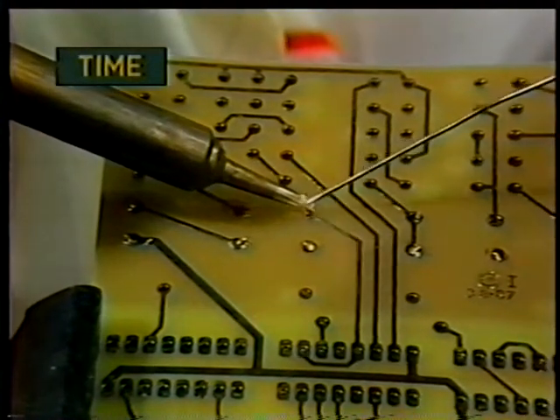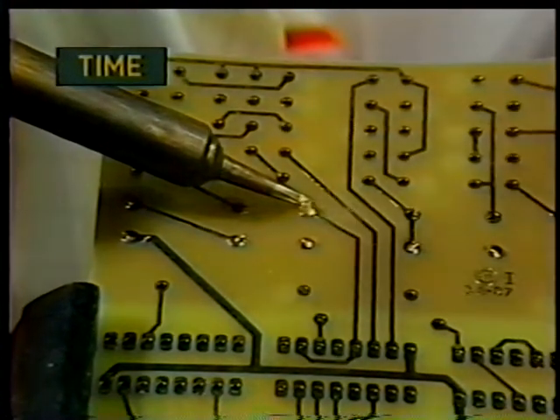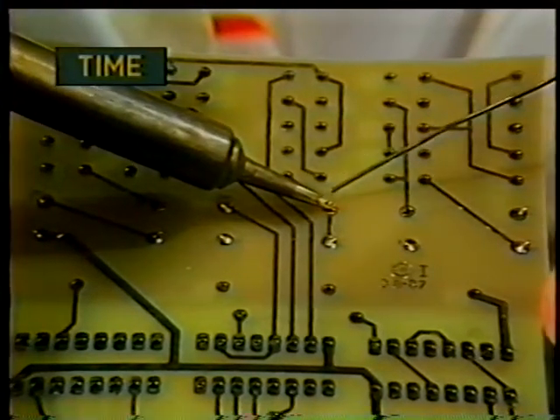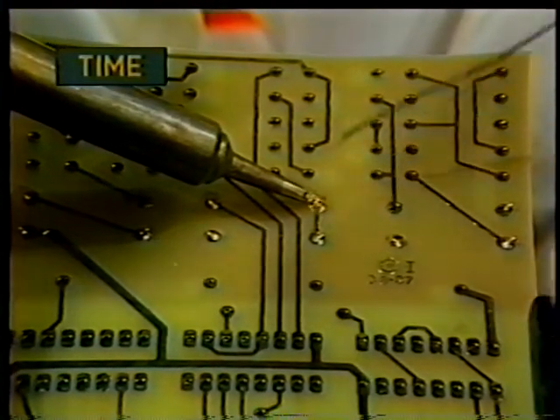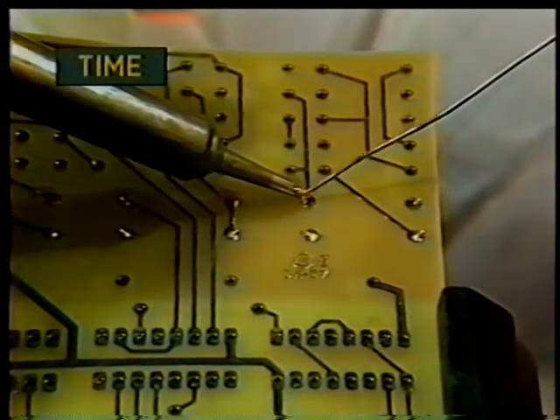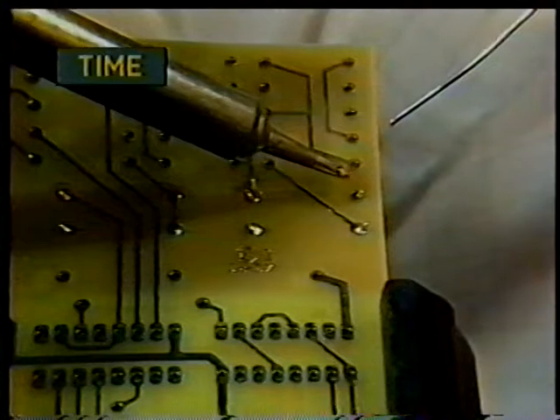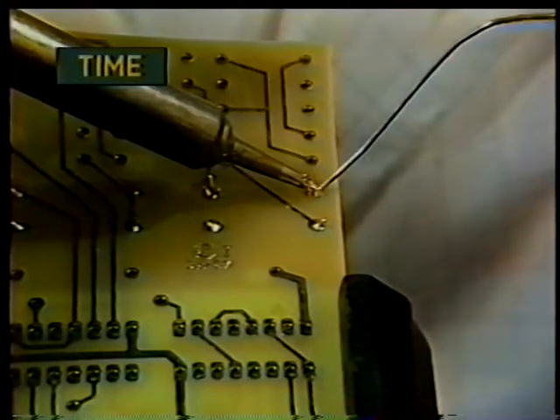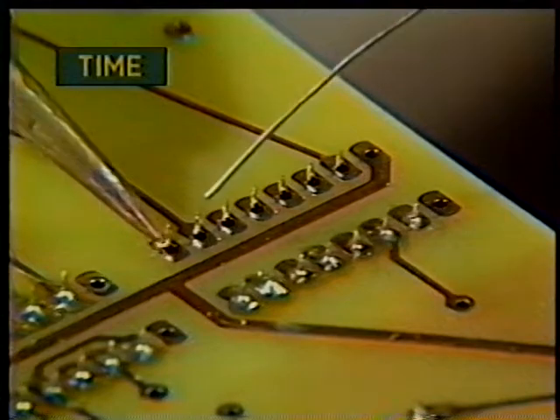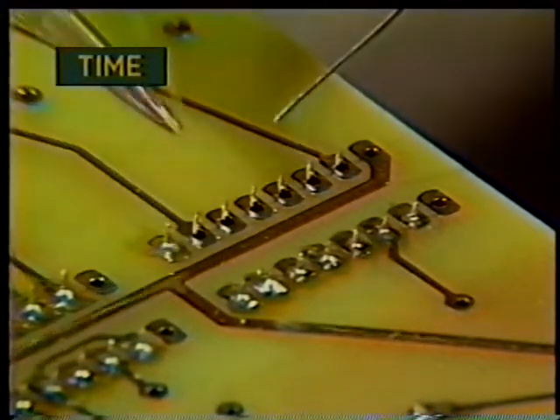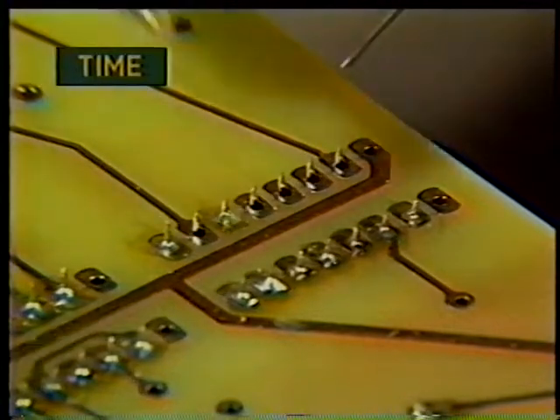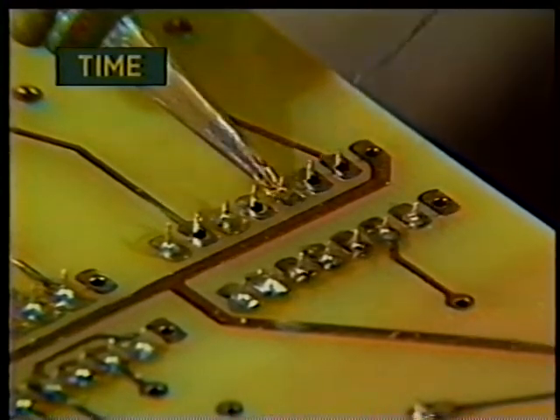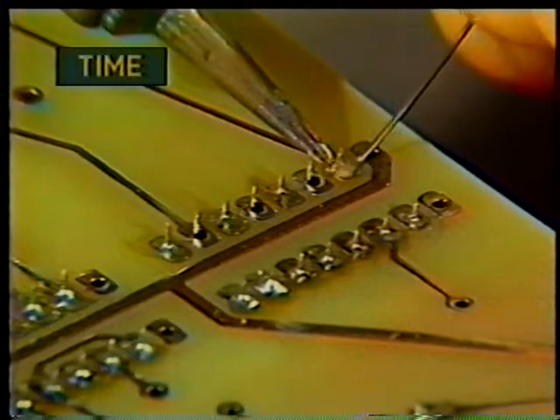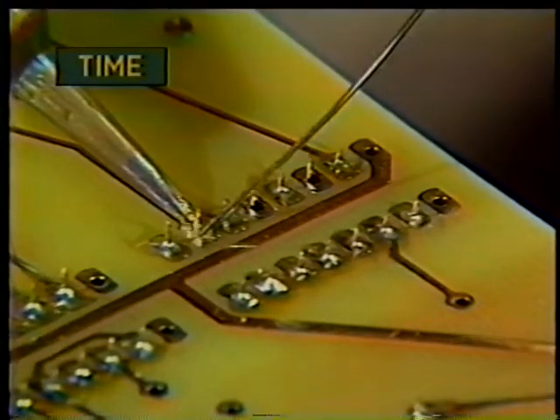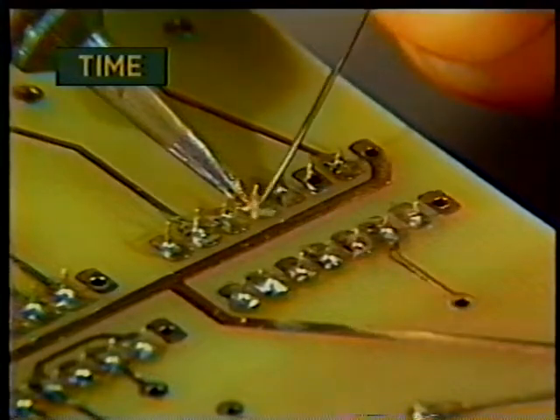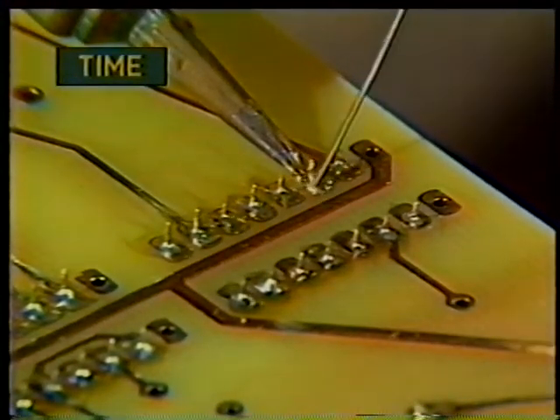The secret to good soldering is learning to recognize the rate at which heat is flowing into the joint. This means observing how fast the solder melts, which should be within 1 to 5 seconds. If the tip of the iron is too small for the work, it will produce a mushy kind of melt. The heating rate will be too slow. If the tip of the iron is too large for the work and too hot, the heating rate will be so fast that it can't be controlled. A good rule for preventing overheating is to get in and get out as fast as you can when you see a good connection has been made.